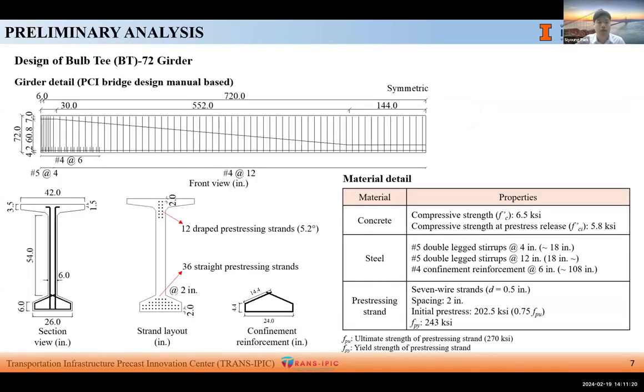Before applying SMAs, to verify the numerical model, a BT72 girder bridge model was designed based on the PCI bridge design manual. The length of the bridge was designed as 120 feet with end stirrups up to 18 inches, 36 straight pre-stressing strands and 12 draped pre-stressing strands, designed with 7 wire strands in a diameter of 0.5 inches with applying pre-stress of 202.5 KSI. All these stirrups and confinement reinforcement satisfy the recommendation of the AASHTO LRFD specification.